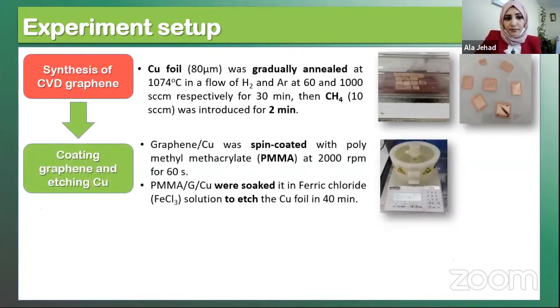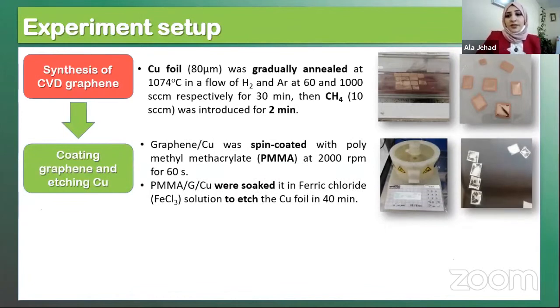The next step was protecting the synthesized graphene. We used PMMA to protect the graphene, spin coated at 2000 RPM for 60 seconds.